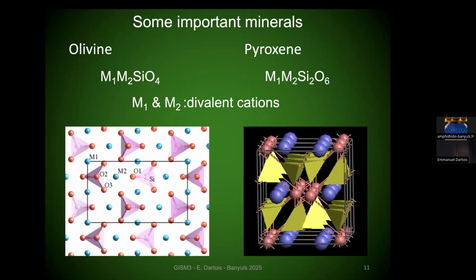You see here that olivine has a tetrahedron of oxygen linked, and there are intermediate divalent cations at different positions in the matrix. The result of this is that for 2 divalent cations, you need 1 silicon atom and 4 oxygen atoms. In the case of pyroxene, which is another flavor of these minerals, you get again the same kind of formula, except that some of the oxygen atoms are shared in the chain in the crystalline structure, and so you get something which requires only 3 oxygen atoms per silicon. So it has an influence. What you can form also depends on the elemental abundances you get, in addition to the physics related to these minerals.